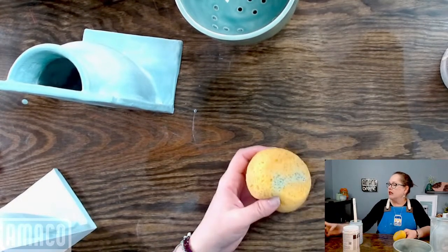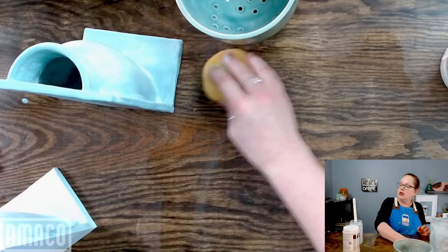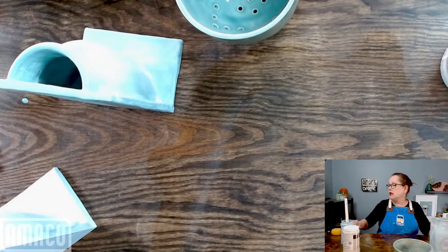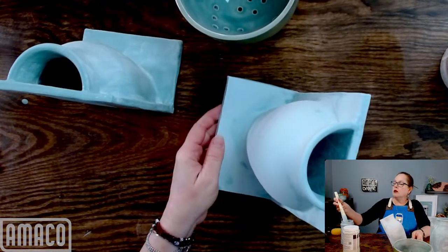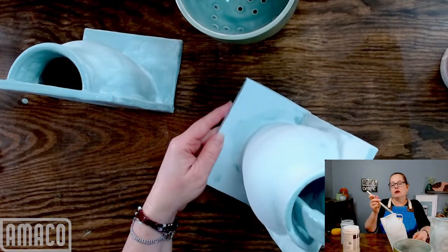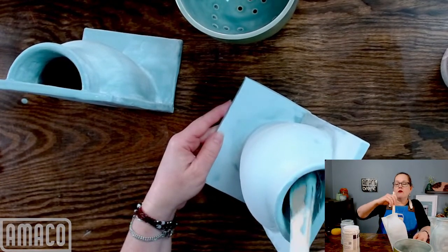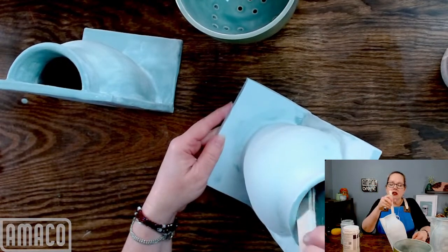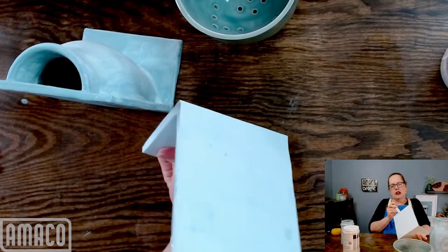Rachel is asking about the black underglazes. Jet black or velvet black flux slightly at cone 6 and stick to shelves, and ultra black. So Rachel, jet black will flux and will stick to kiln shelves at cone 6. Definitely. When it comes to velvet black, it will not stick all the way up to cone 10. However, we have had people experience velvet black sticking at cone 6 when it was a very, very heavy piece. So the weight can actually push the underglaze and encourage it to stick. So if you have a very heavy piece, I recommend not using an underglaze on the foot.